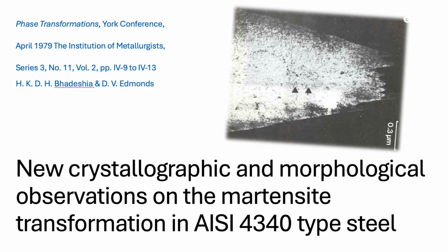Right. In those smaller grains, they mainly saw what was termed half-lath morphology, sort of underdeveloped lath structures. But once the grain size got bigger, above that 100 micrometer threshold, that's when they started observing fully formed plates, sometimes quite large, both inside the grains and crossing grain boundaries. So larger grains provide the necessary real estate for these big, likely high-strain plates to form. It seems so. Space is a critical factor.